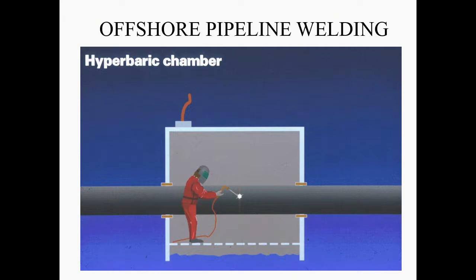Hyperbaric chamber. Well, in a hyperbaric chamber, it's some kind of box which simply needs to offer protection against the seawater, which is fitted onto the pipe at the location where the weld is to be carried out. And you put the welder in, and you see this. That's a tube through which, in many cases, air is pumped. Because of that, somewhere at the bottom of this hyperbaric chamber, on this line, the pressure in the chamber equals the pressure in the sea. But as you go up, the pressure increases.